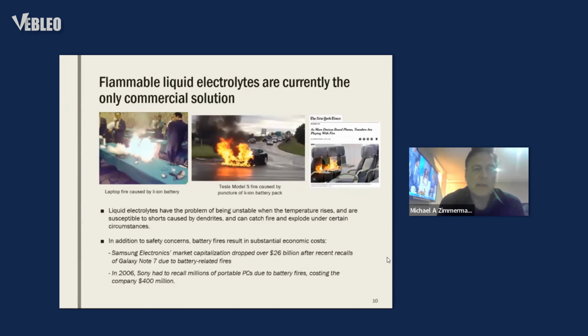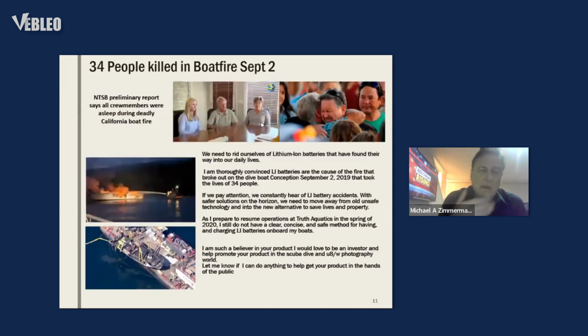So the major issue that people hear about in the news is the fact that the liquid electrolyte is volatile, and there have been many reports about airplanes, things going into thermal runaway, things like Teslas, where the battery goes into thermal runaway, and the problem is it's very difficult to put the fire out. There's been news about laptops where the batteries do explode, and it's being blamed on the liquid electrolyte, which is volatile. I'll talk a little bit more about that.